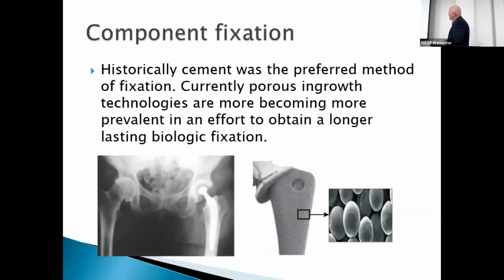And a little bit about component fixation. We have two ways essentially of fixing these parts to the bone. One is using that methyl methacrylate glue that I talked about. And the interesting thing is methyl methacrylate is the same material that makes plexiglass windows. So that was interesting to find out. But we use that. It's very stable. It's very good. And this is a cemented implant where you can see the implants here. The halo of white around it is cement that's fixing it to the bone.